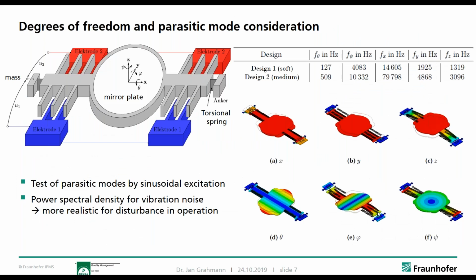So that brings us to the point that we can use that piezoresistive sensor in a test setup in order to detect how the mirror moves during operation and their vibrational influences, which without that integrated position sensor would be quite a challenge, because somehow you would have to do it optically, and at the same time that setup would have to be resistant to the actual vibration put on the measurement setup. So we clarified how we will be able to measure the actual influence of vibration.